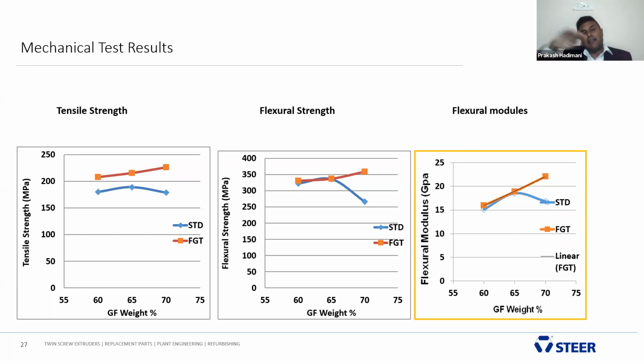And in the flexural strength, the same phenomenon happens. But for both standard and FGT at 65% filling of glass fiber, it's the same. Okay, not much change. The moment of addition of another 5%, it goes to 70%, the flexural strength of the standard technology came down drastically. But in the case of FGT, it's increasing. That shows the dynamic stirring elements hold the glass fiber. The wetting was happening, and the distribution is helped by the fractional geometry technology, like FGT, we call it.